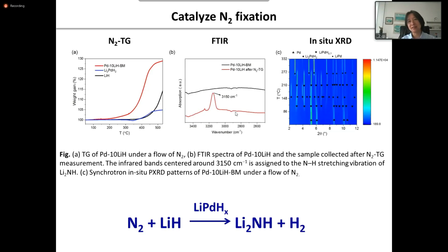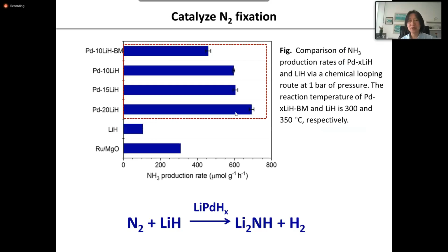So that gives us a very good idea that we should use this complex hydride as a catalyst to fix dinitrogen. By doing so, we are able to achieve a pretty high nitrogen fixation rate as well as ammonia production rate by adding palladium into the hydride system. So lithium palladium hydride would be a very good candidate to catalyze ammonia formation.